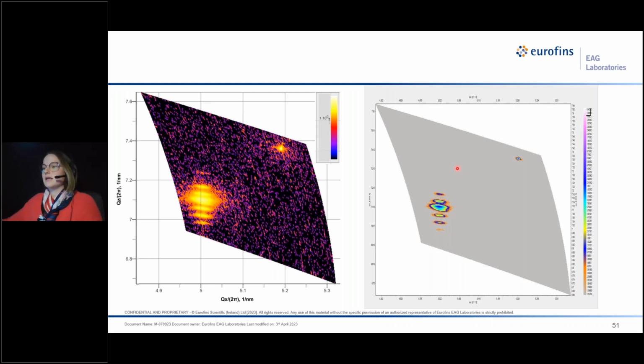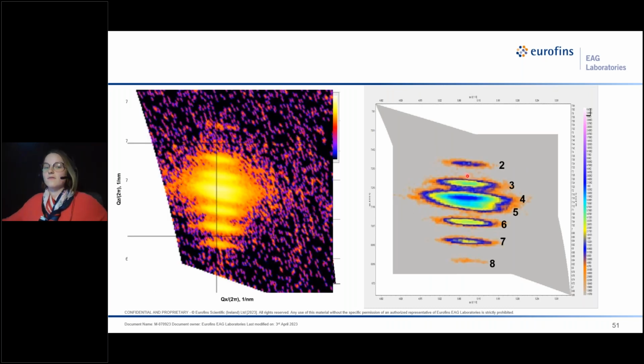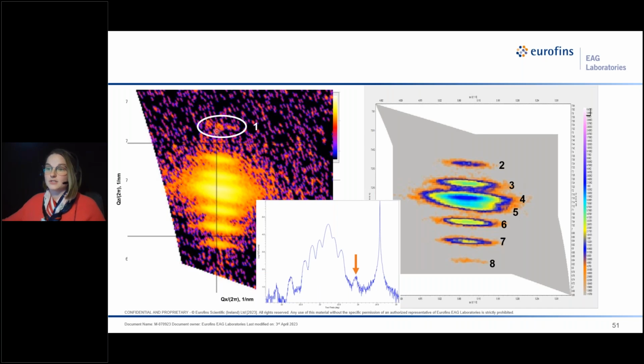Now, what you can see here is that the substrate peak is all the way up in this top corner, and that means that all of the layer peaks are completely dislocated, completely relaxed from the substrate, because this is composition. Now, up and down is strain. So if we zoom in, we can see that all of the layers are completely strained but have different compositions. And so in the previous case, we could only see 7 of the peaks, but with our newer diffractometer, we can actually see the 8th or 9th peak.